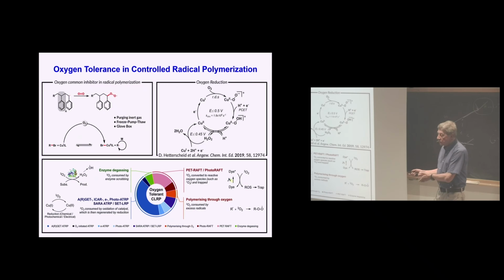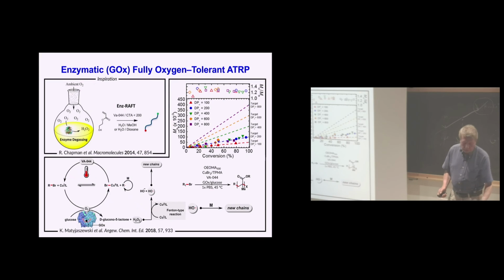So can one do something similar in a controlled radical process? And in fact, you can do that because the product, hydrogen peroxide, is not a good radical initiator. Which means that if you run a RAFT polymerization with these compounds, you can have these multifunctional initiators and you will not generate new chains, you would form just a star or bioconjugate or something else.